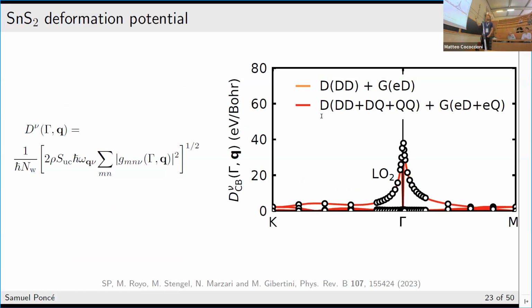So one way to quantify how good this interpolation scheme is, is to look at the deformation potential. So the deformation potential is a way to probe the electron-phonon matrix element. So here I'm showing the deformation potential of SnS2 as a function of q, and you can see that it interpolates very well. So what is happening is that the lines are computed on a very coarse grid. So only a few q points in the grid, and then you do the interpolation and you obtain these lines. Instead, all the dots are independent direct DFPT calculations just to verify that we are interpolating indeed correctly, and you can see that it works quite well. On this scale, you have the optical mode that dominates, so you don't see much. But basically, I'm showing the interpolation done with only dipole term, and the one including dipole and quadrupole.